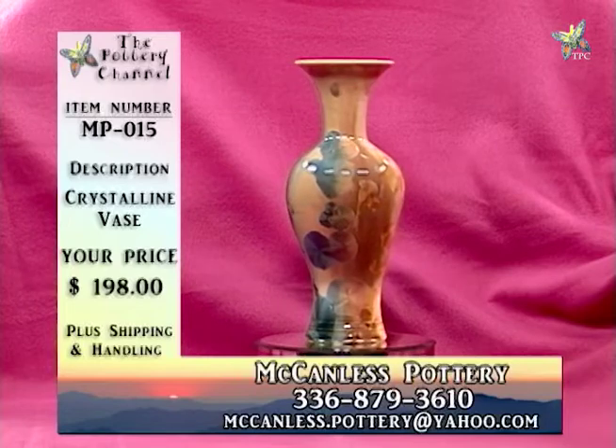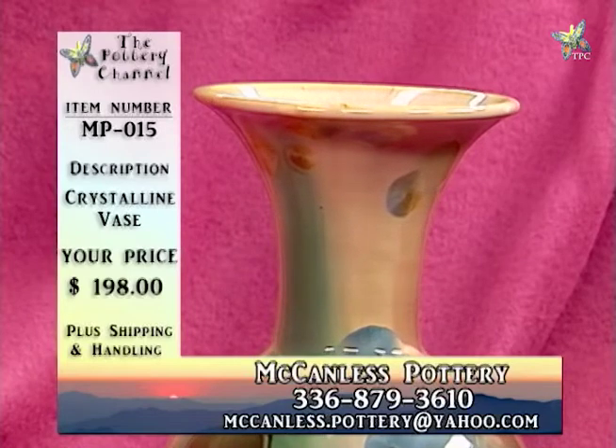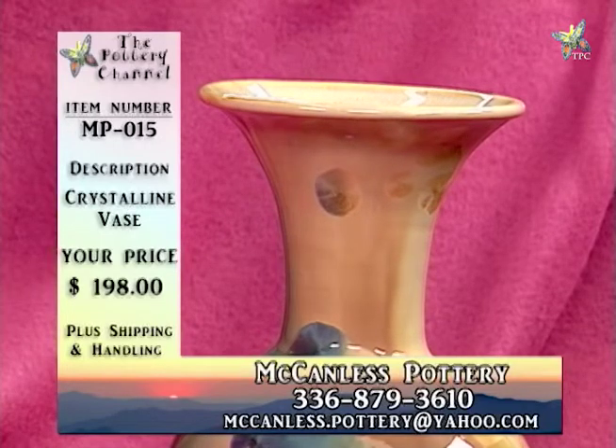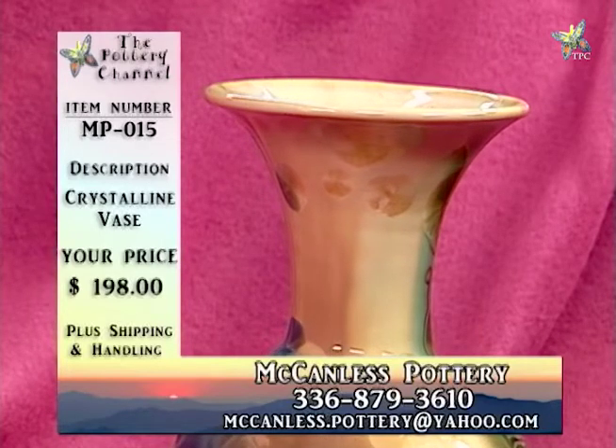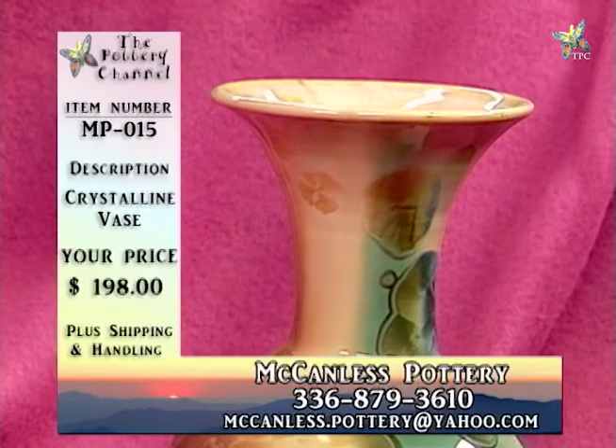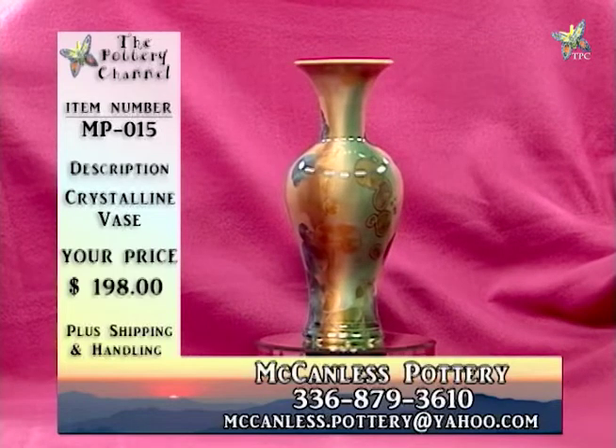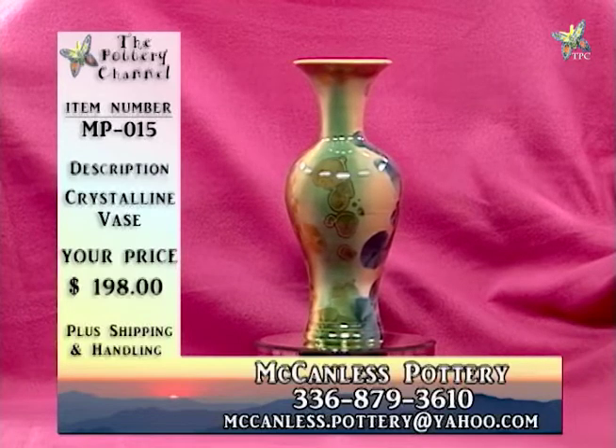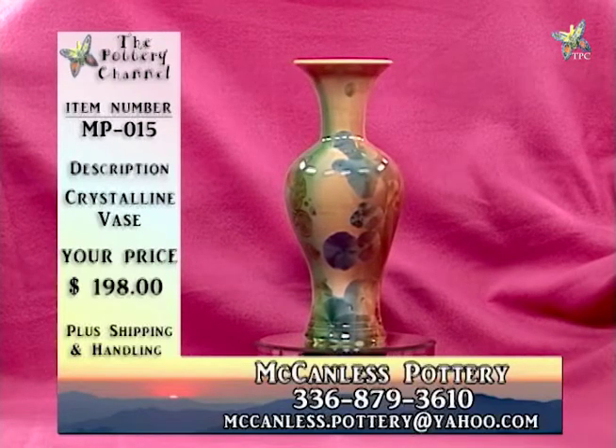Multicolored crystalline vases are the most popular for obvious reasons — there's all that color. Generally, people really like brilliant color. You've got a variety of color on different sides of the vase and you can turn it a different way a different day and almost have another vase. To accomplish that, I'm mixing up several zinc silicate crystalline glaze batches with the only difference being the color added to those batches. Then I'm applying a particular glaze batch to the portion of the pot I want to be that color. The zinc silicate crystals are going to grow regardless of where the metallic pigment is, so that's how I achieve consistent crystals but color in different areas.